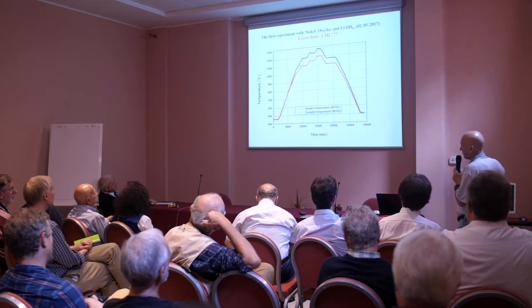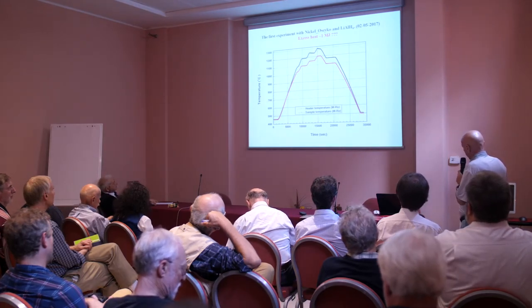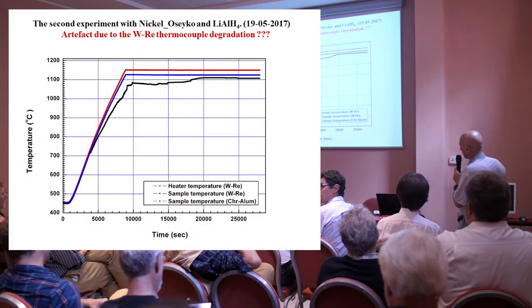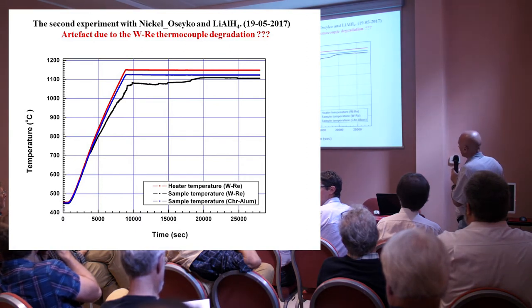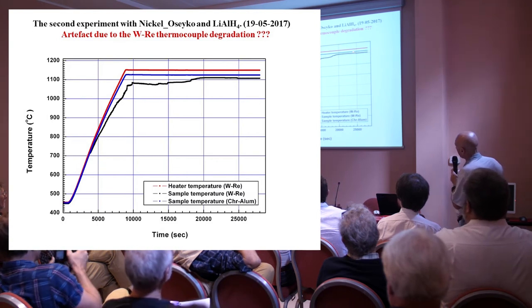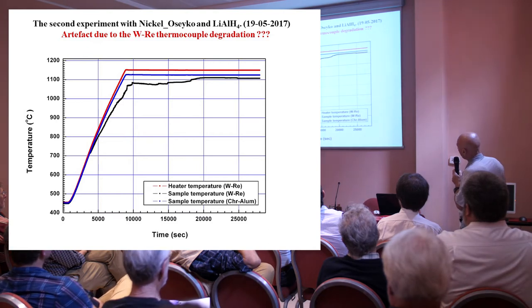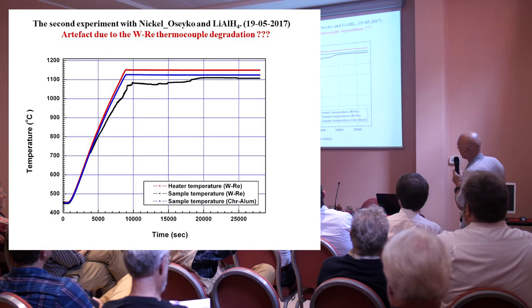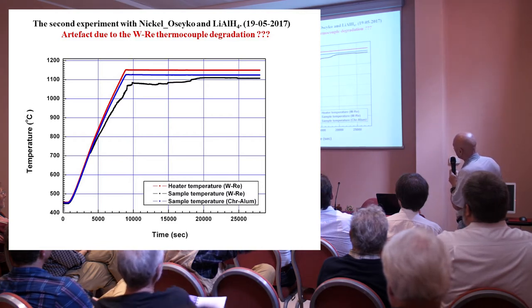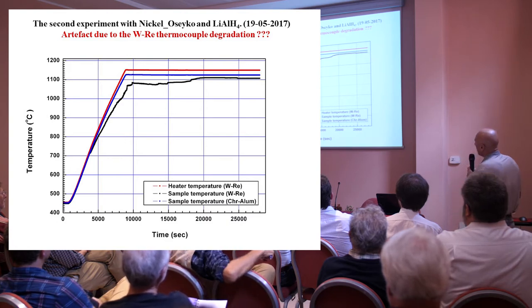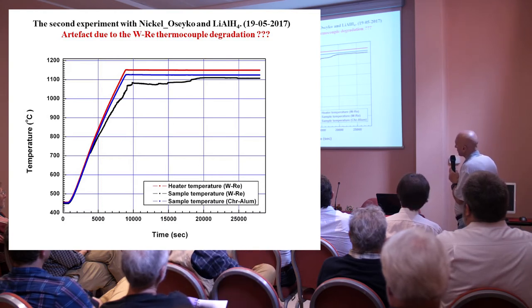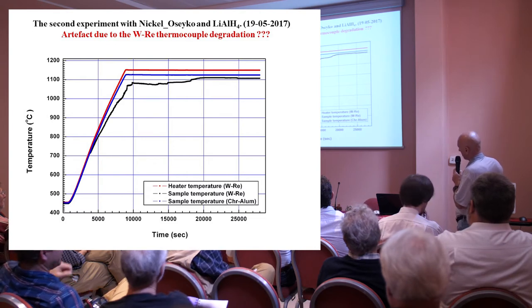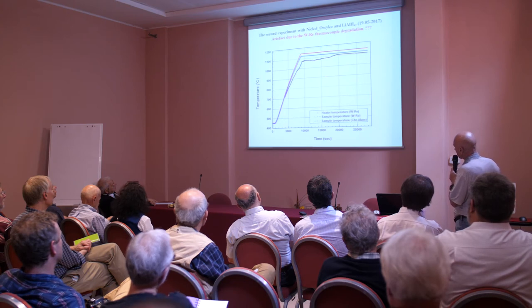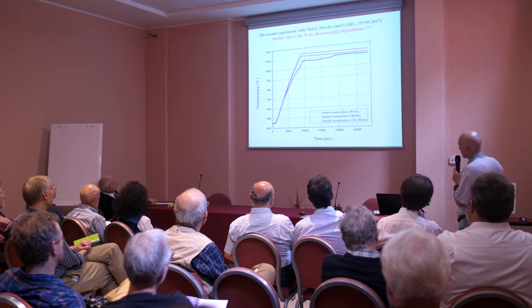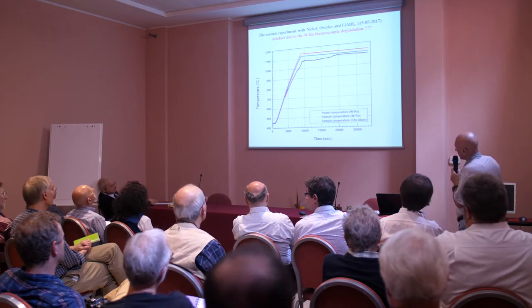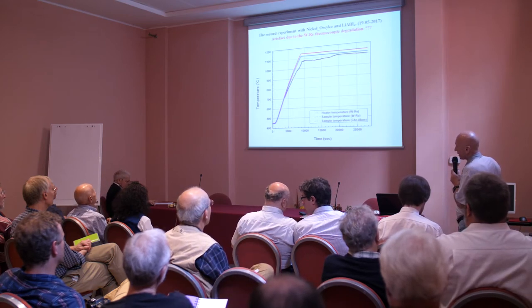And in pure hydrogen, it behaved very well, well above 1,000 degrees, say. But we did another check with 2 types of thermocouples integrated inside the fuel. So then you see the red one, it's the readings of the heater, and this blue is the K type, chromel, alumel, and the tungsten rhenium is the black one. Quite surprisingly, after the same temperature, it started deviating, but not up, not above, but below. Yeah, and if that were true, one could say, okay, we have not energy production, but energy consumption. But alas, you can see that another thermocouple doesn't show any sign of unusual behavior.